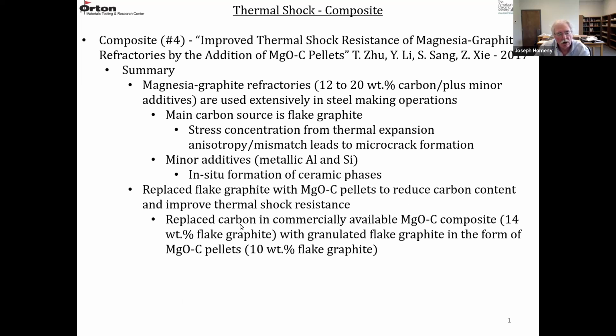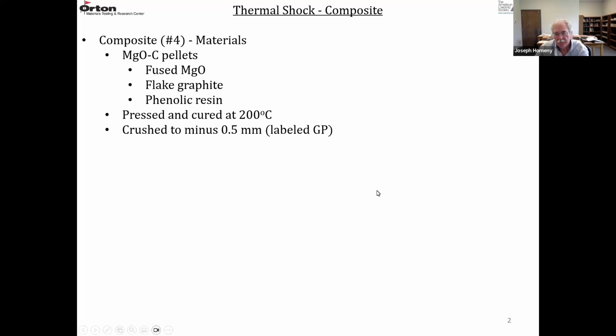So the carbon content in a commercially available MgO carbon composite, in this study, the one they looked at was a 14 weight% flake graphite, and they tried to lower the carbon content with this granulated flake graphite in the form of these MgO carbon pellets to get the flake graphite content down from 14 to 10 weight%. The flake graphite is a costly component, so part of this effort was probably to reduce cost.